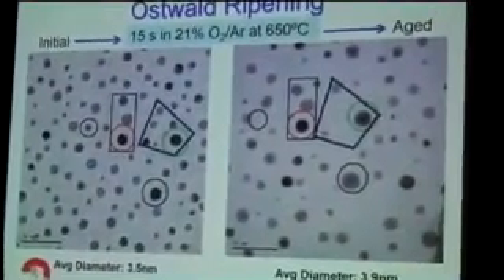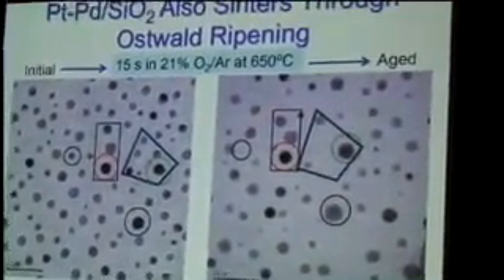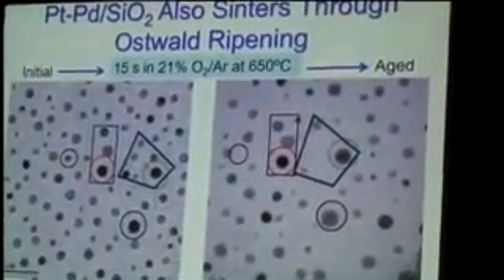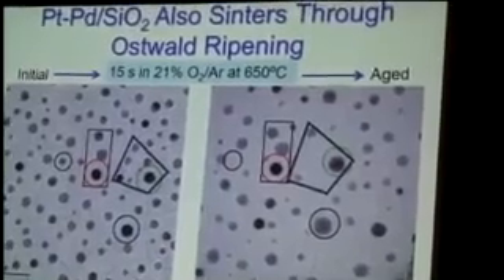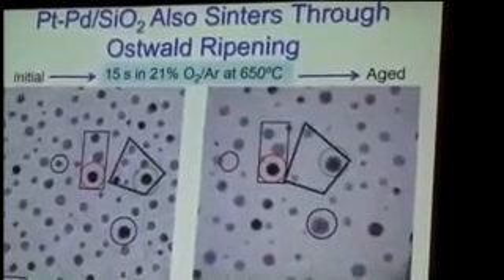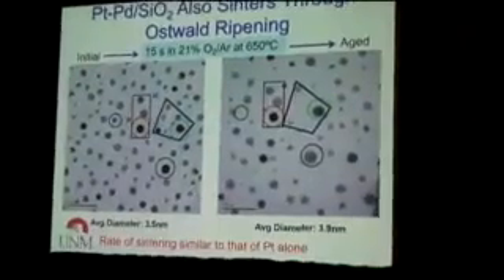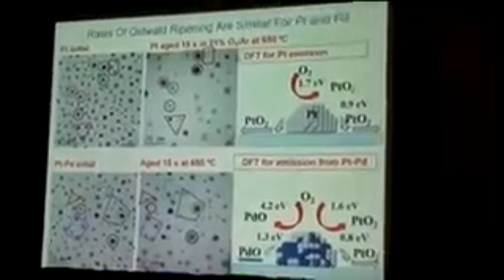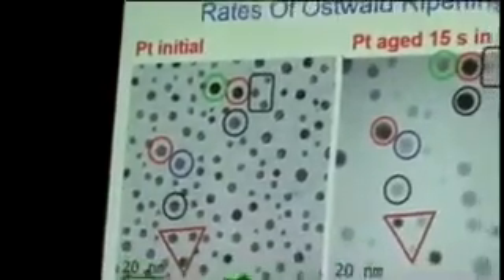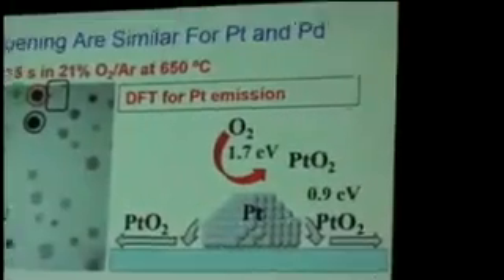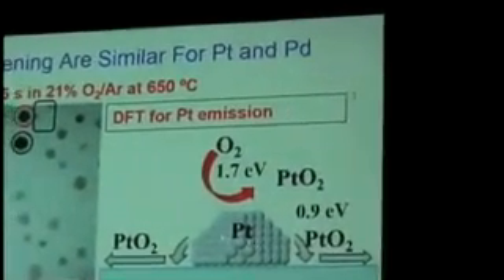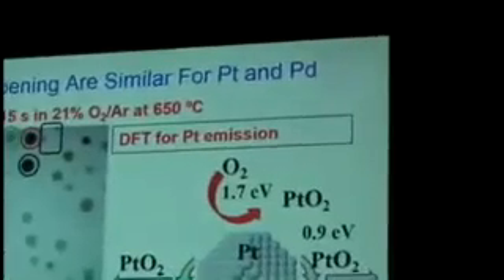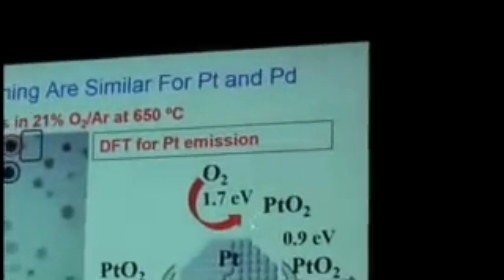And the palladium only happens if you start from a metallic particle. If you start from an oxide, it doesn't move because PdO is not volatile. Platinum palladium, however, does show similar behavior. You do some DFT calculations to find out is it possible, what is the barrier for emitting platinum in the form of an oxide. So if you emit platinum oxide and put it in a support, the barrier is quite low. You put it in the vapor phase, the barrier is higher.